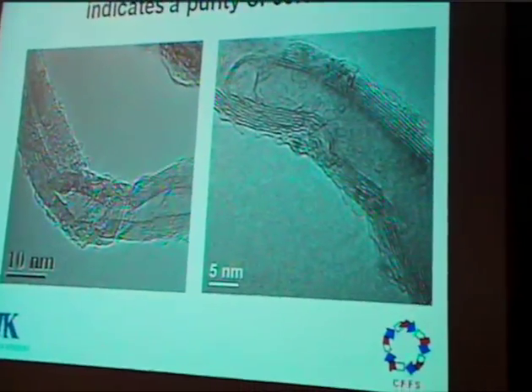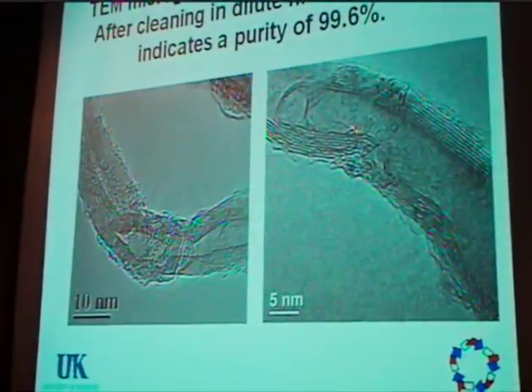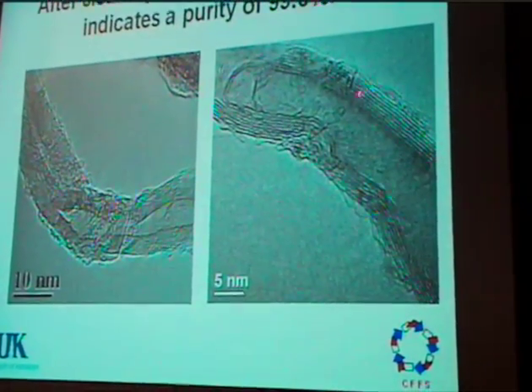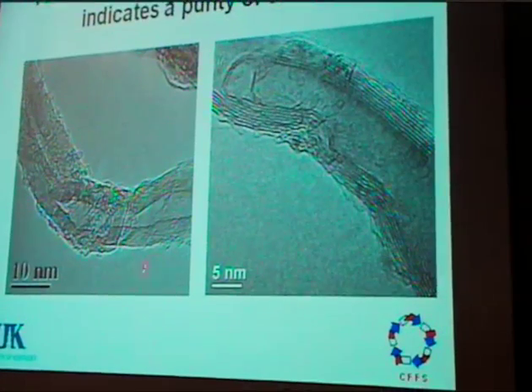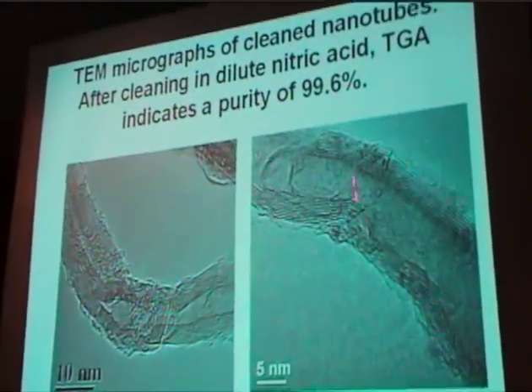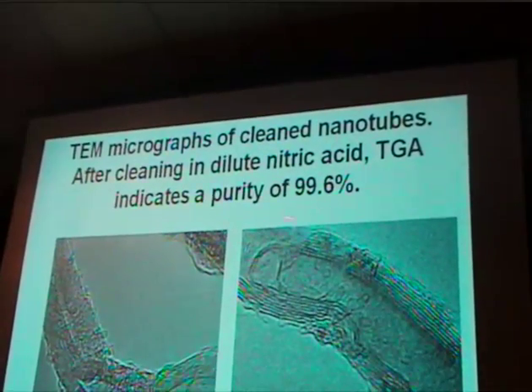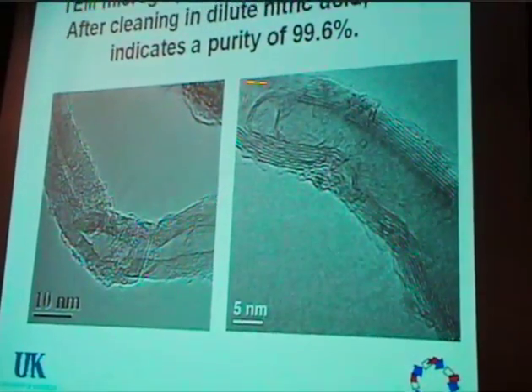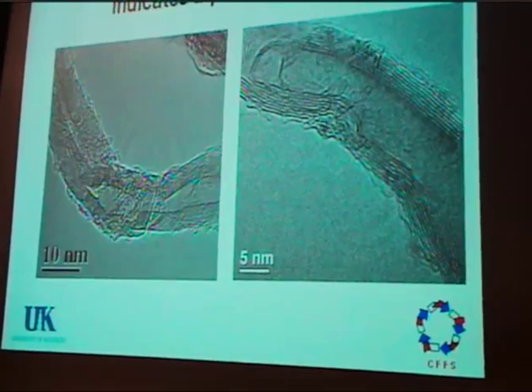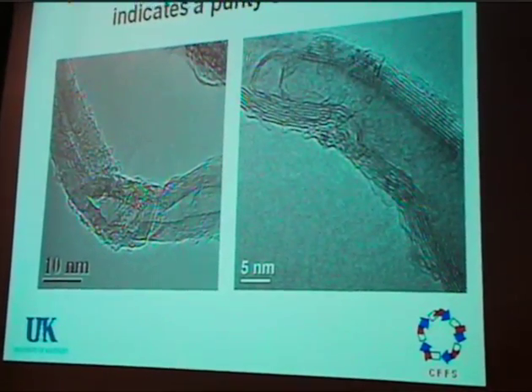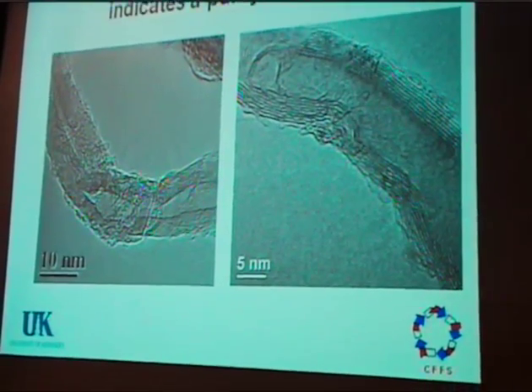And these are some micrographs of the cleaned nanotubes. These were produced in a more active region, and so they're all multi-wall nanotubes with parallel walls. And TGA indicates that the purity of this particular sample is about 99.6%. So that's a pretty good result. And this is done just in dilute nitric acid, which is a fairly easy cleaning process.